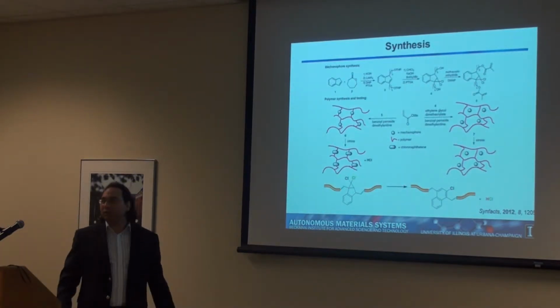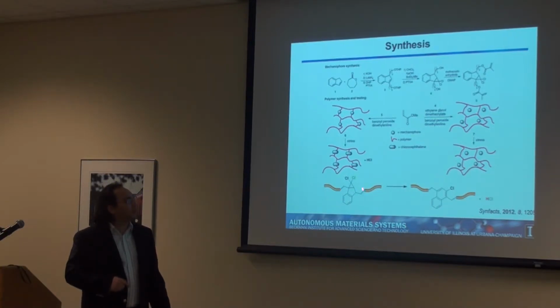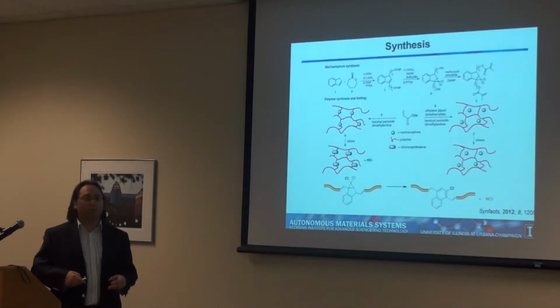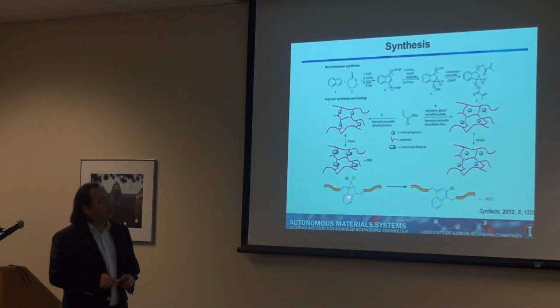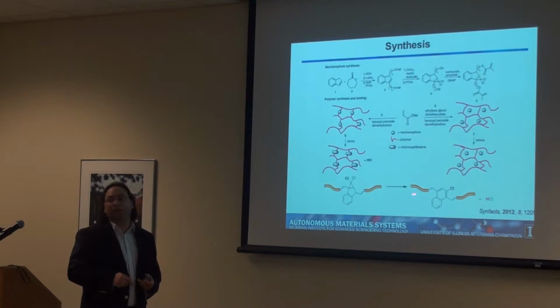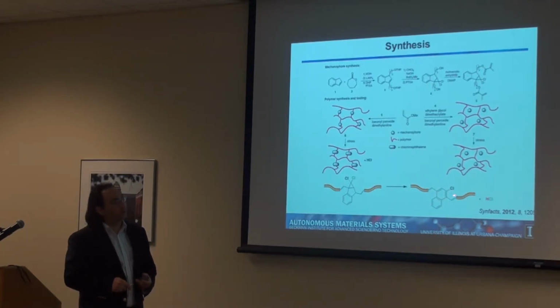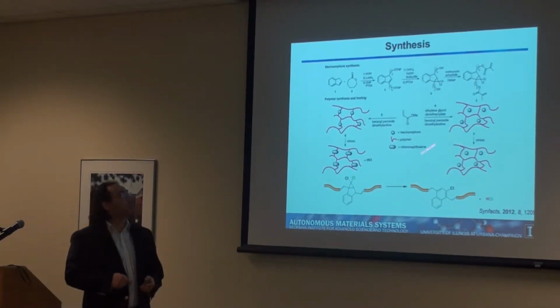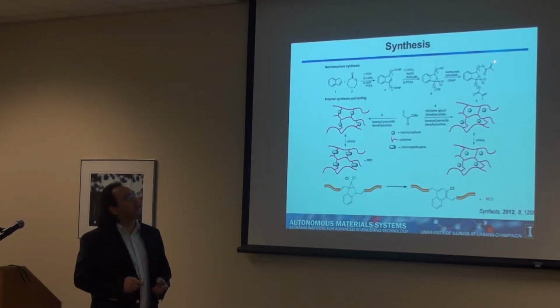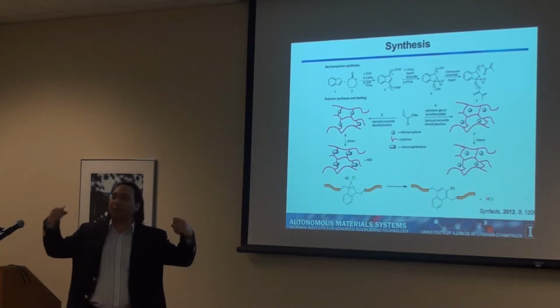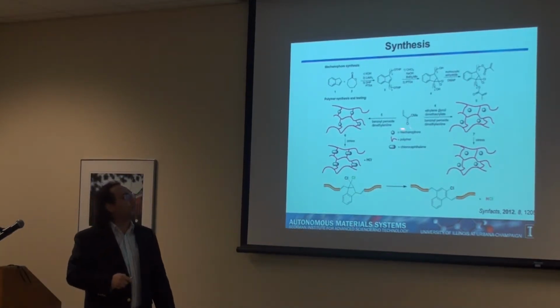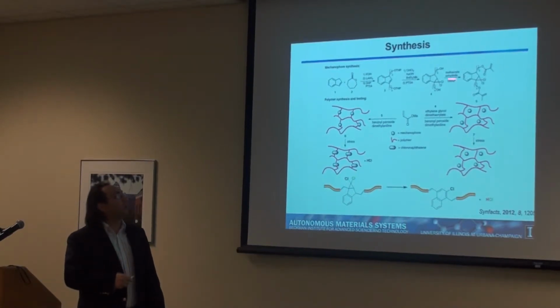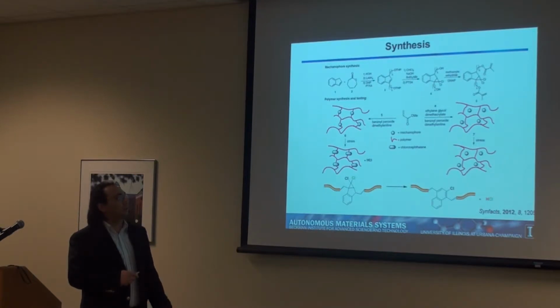This is the chemical synthesis. I won't go through this. But basically, we made this small molecule and incorporated it into the polymer. It has the dichlorocyclopropane in the 5-membered ring with the double bond here. Our idea is that if we apply mechanical force to that, maybe it will undergo the 2 steps and do elimination, produce the acid, and aromatization is what's going to drive this last step forward. This is the molecule that I made. It has 2 methacrylate groups, one on each side, so that it can bind the polymer from both sides. We polymerized methyl acrylate, a common monomer, in the presence of this as a cross-linker. So we just get a thermoset where we have this group cross-linking between the chains.